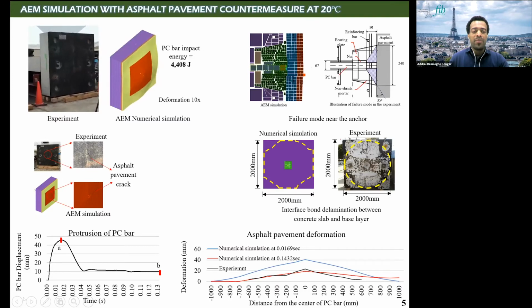This is PC bar displacement versus time. When the bar is impacting, it moves forward, but at this location, at this time, the PC bar lost almost all of its strain energy while impacting the asphalt pavement and moved backward. We also checked the asphalt pavement deformation along the center line between the two connecting PC bars.